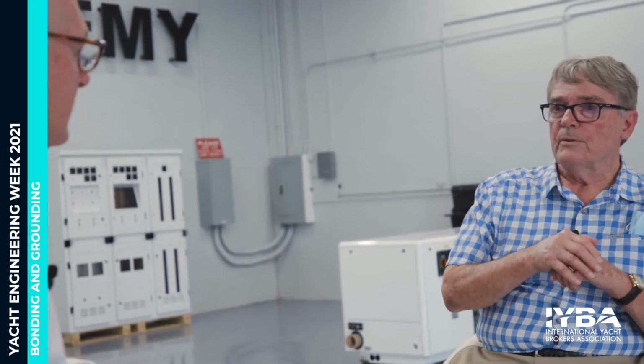Go back to the sacrificial anode system again. I'm going to use some numbers here just to give you an idea of what happens. Let's say a typical fiberglass hull with bronze and stainless steel underwater metals that are bonded. That mixed potential unprotected is probably in the area of 300 or 400 millivolts to silver chloride, as I mentioned earlier. To cathodically protect those metals, we want to raise that potential by at least 200 millivolts. So that takes us up to the area of 600 millivolts for a minimum level of protection.